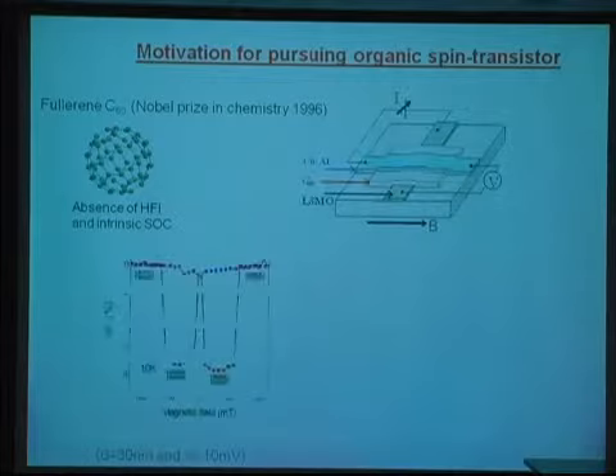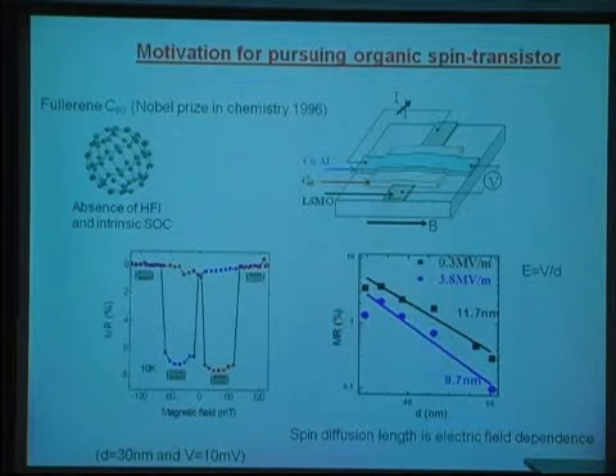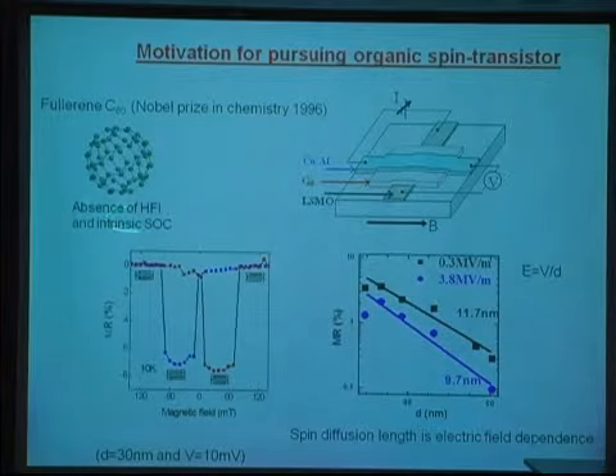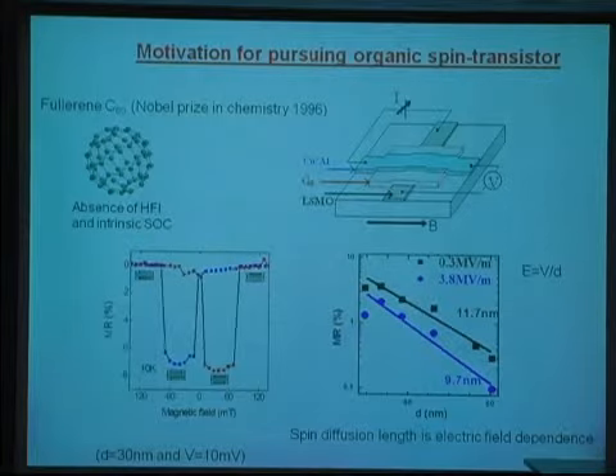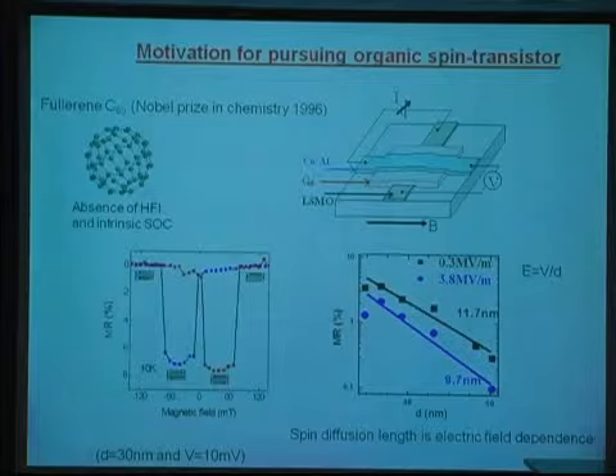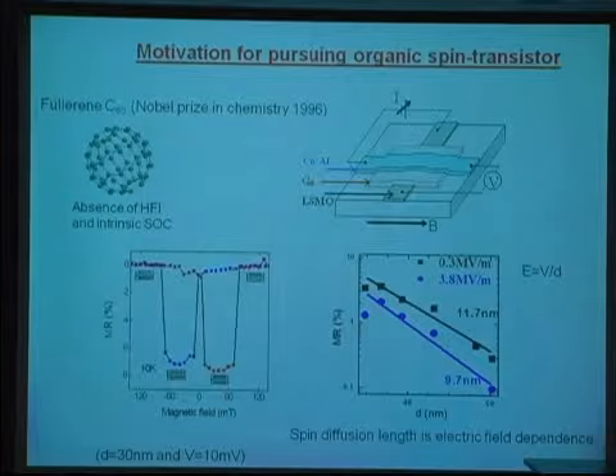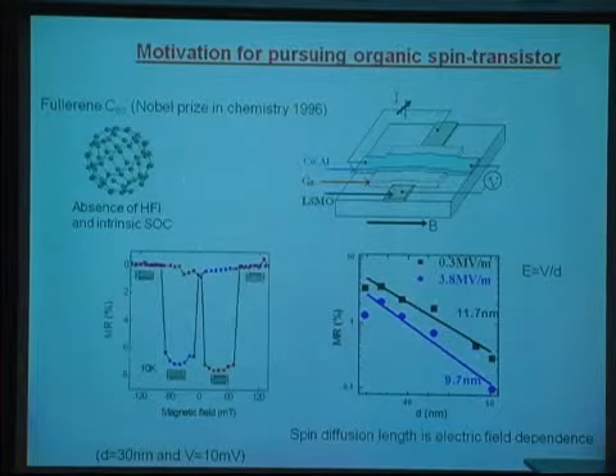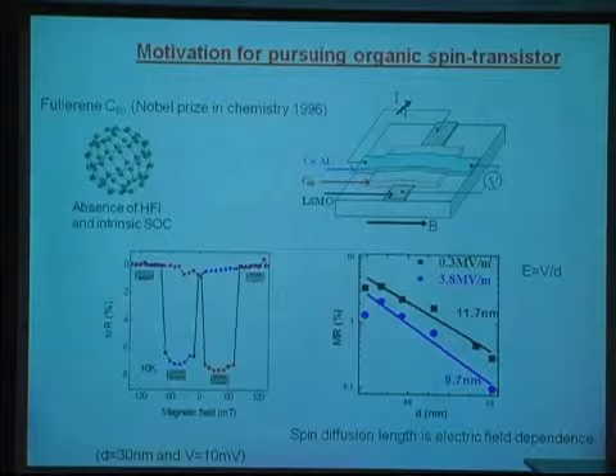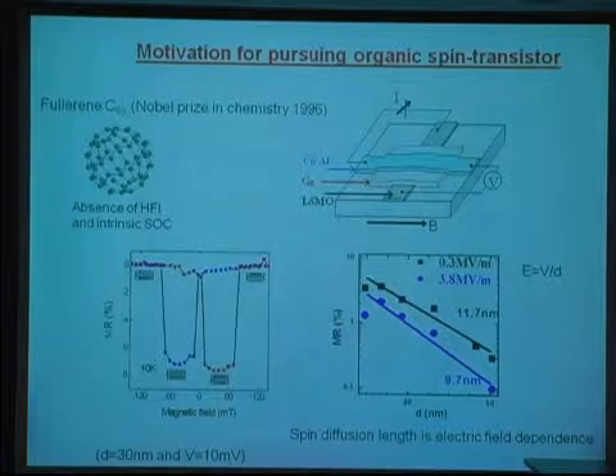Okay, so what I study is the C60 material. In C60, you can see that we don't have much hyperfine interaction, and and absence of intrinsic spin-orbit coupling. Why? Because we don't have the nuclear spin in the carbon C12, and most of the carbon here, 99% of the carbon here is carbon C12. Okay, and you can see here the magnetic response is very nice, and the effect is 10%. It is not 40% like I presented in the DOO-PPV or in the Alq3 device.